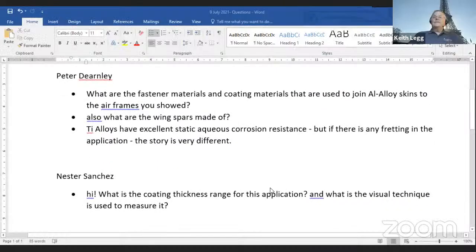Yeah, sure. Typically in older aircraft, the fasteners are high strength steel and they're CAD plated. That's the standard. They're now becoming more fasteners made out of titanium, Ti64, which are not plated. The alloys in the aircraft, typically again 7075 T6 aluminum for the spars, and 2024, which is a copper-rich alloy, for the skin. And so skins tend to corrode very easily. It's a real problem.